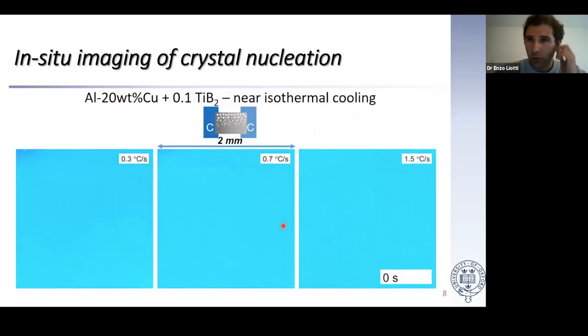Okay, so I'm going to show a first set of data. You can see here there are 3 videos ready to start, and they are an aluminium 20% copper sample, which was added with this magic powder, the grain refiner. The heaters are on the left and on the right, as you saw before, the sample was positioned horizontally, in what we call near isothermal conditions. Near, because there is always a little bit of thermal gradient. And the difference between the 3 videos is the cooling rate.